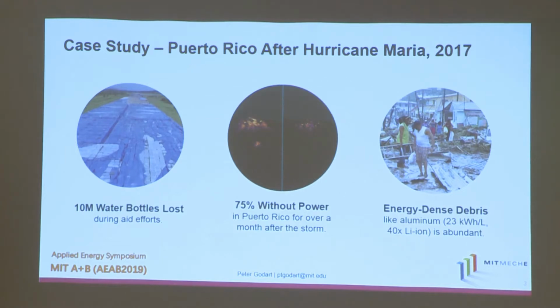But what people don't realize is that a lot of this debris is actually incredibly energy dense. In particular, aluminum has an energy density of 23 kilowatt hours per liter. That's 40 times the energy density of lithium-ion batteries. And after a natural disaster like a hurricane, aluminum debris is incredibly abundant because of damaged cars and homes which use aluminum as construction materials.